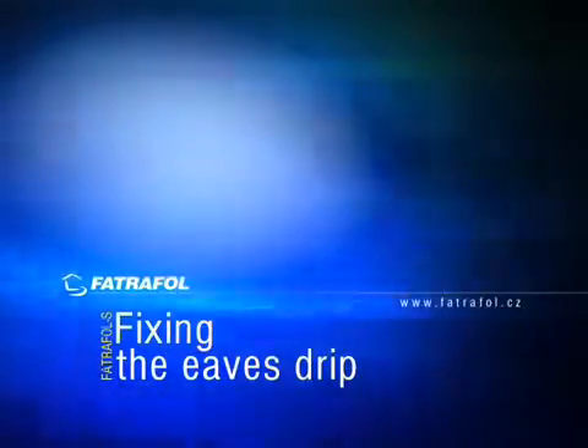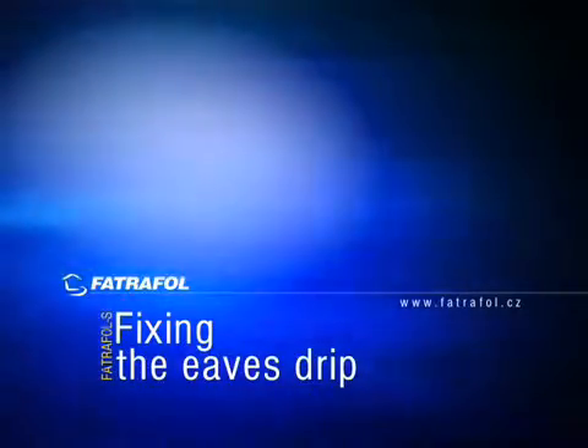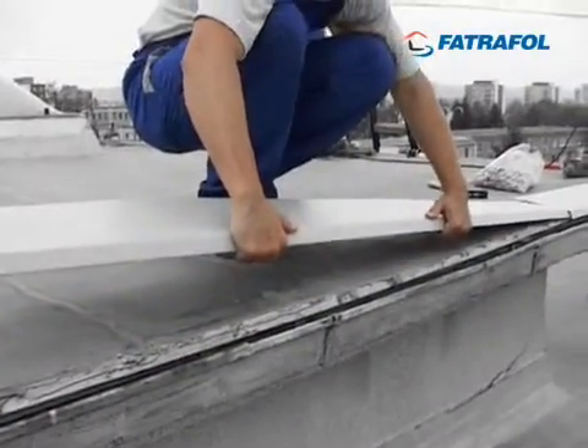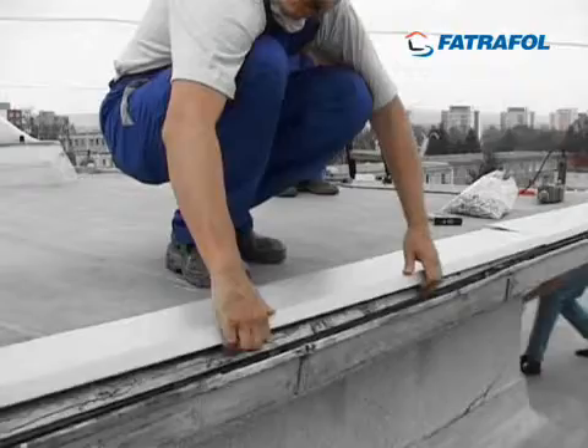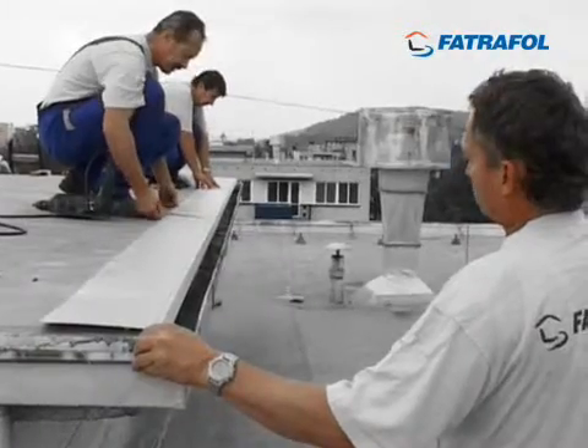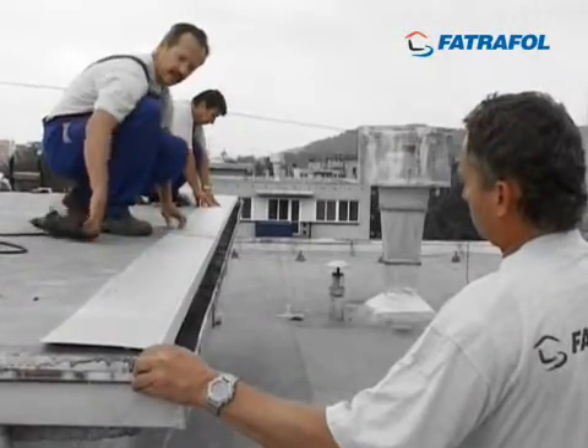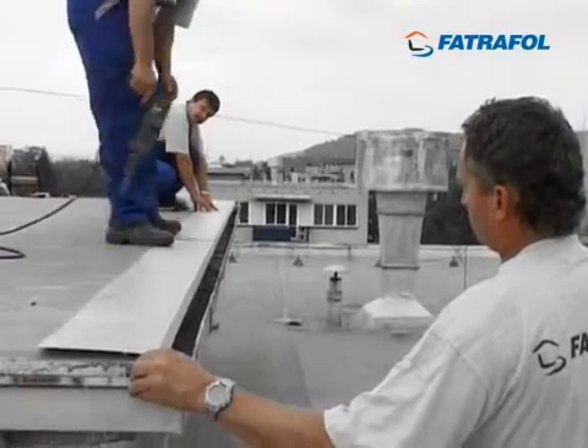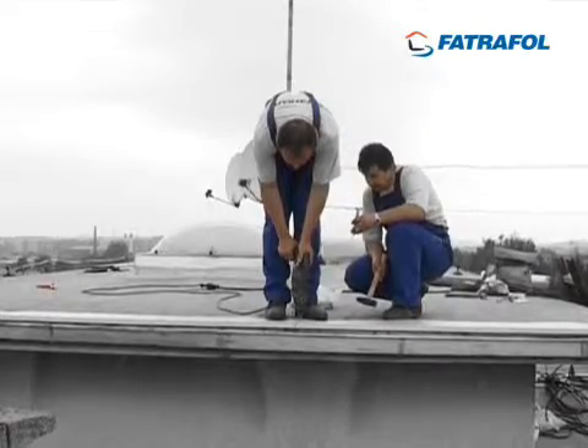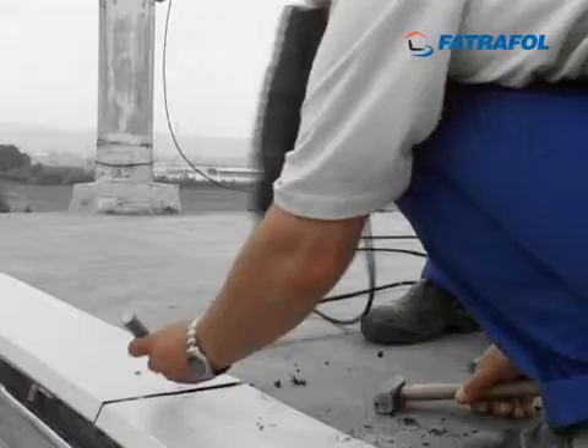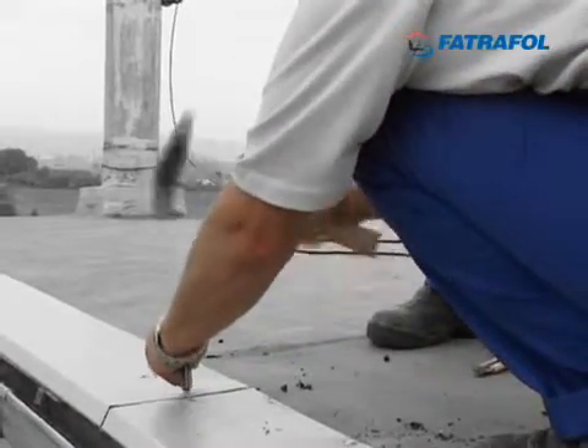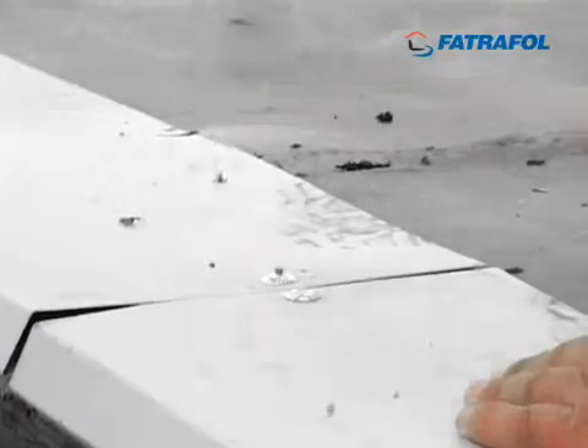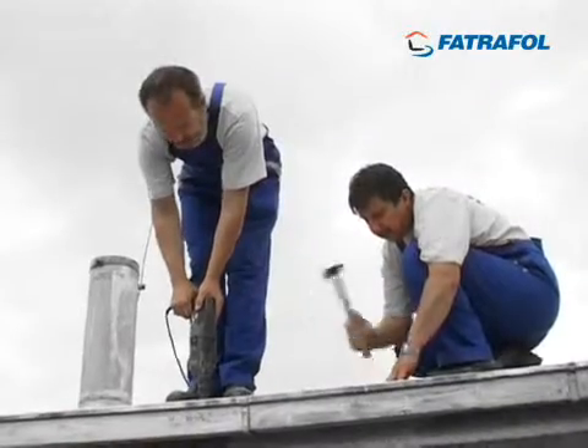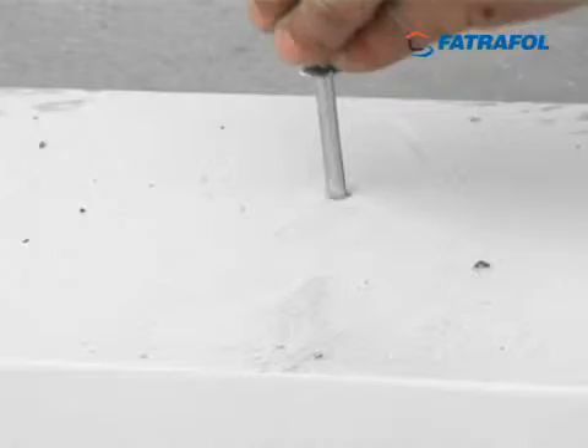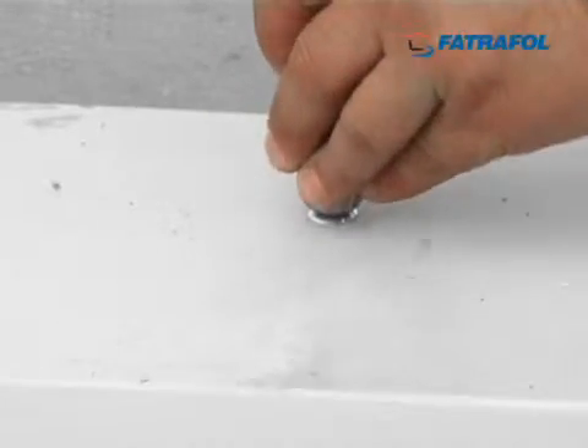Fixing the eaves drip. Install and align the PVC coated metal profiles, keeping a gap of 2 to 3 mm between them. Use the fixings to attach the profiles to the base. The fixings must be spaced at 160 to 200 mm. If the PVC coated metal profiles are wider than 200 mm, we recommend fixing them in two lines for better lateral rigidity.